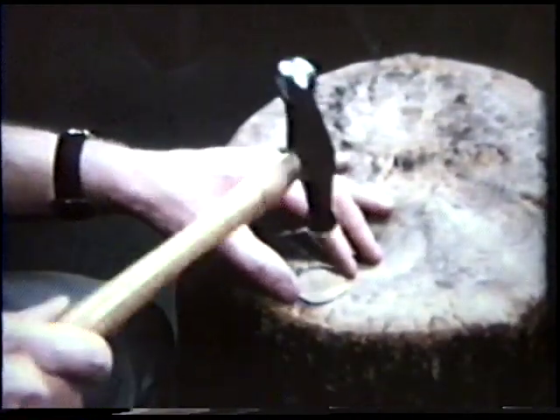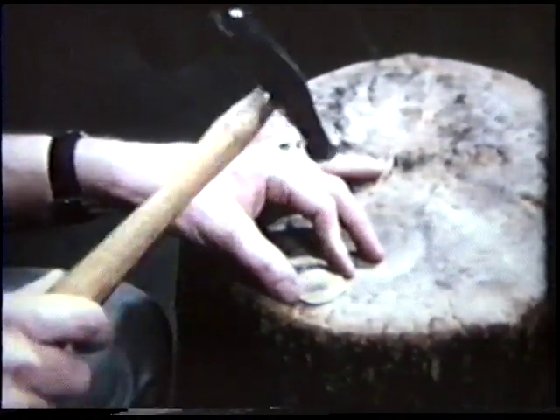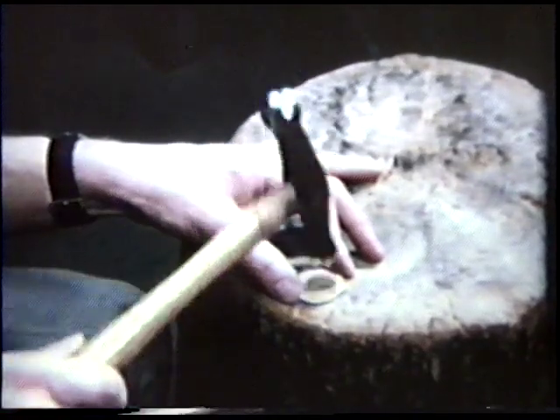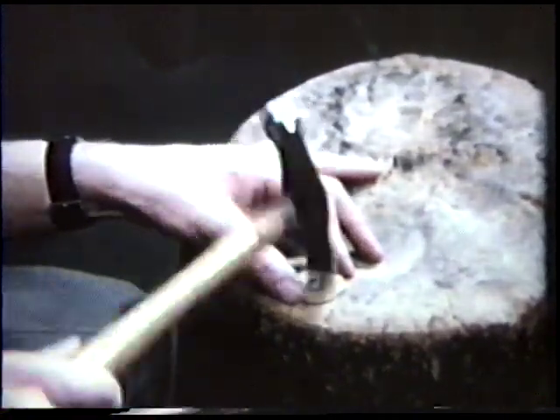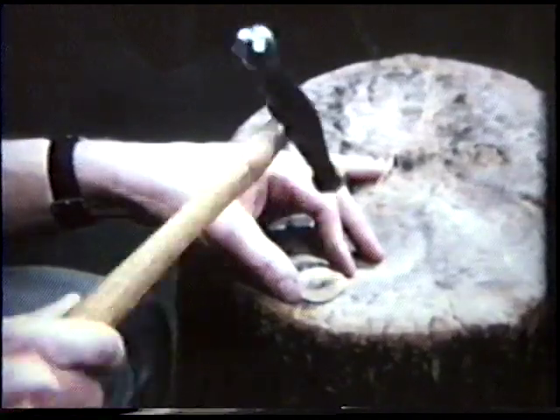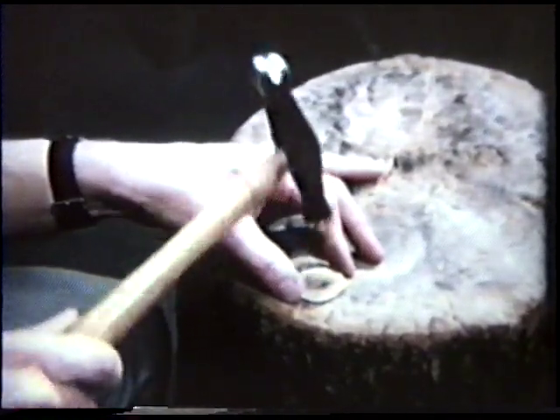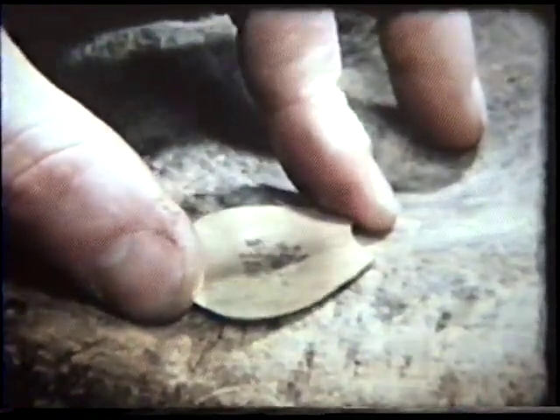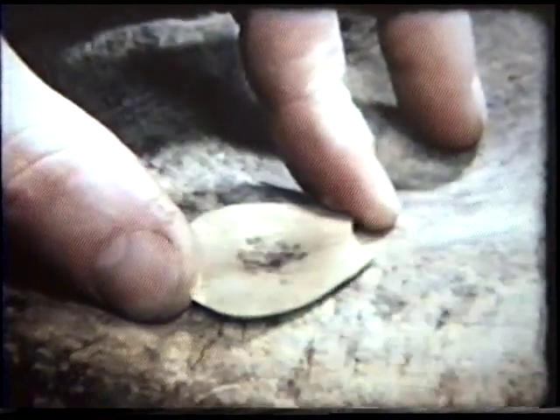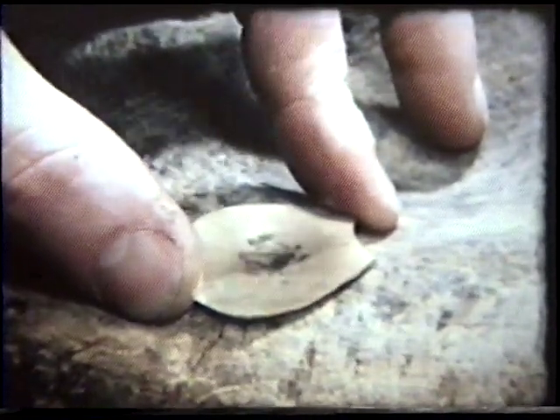The first forming of the back is done with a small ball-peen hammer on a block of wood or stump. This does not change the thickness of the metal to any great extent, but the piece gradually assumes a cupped form, retaining the original size and contour of the edge of the shape.